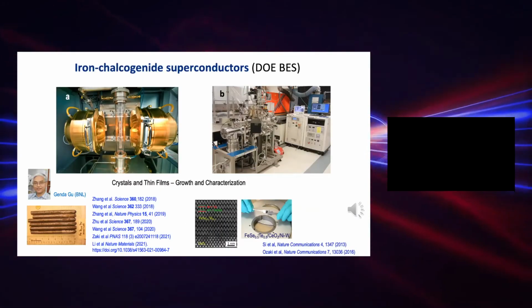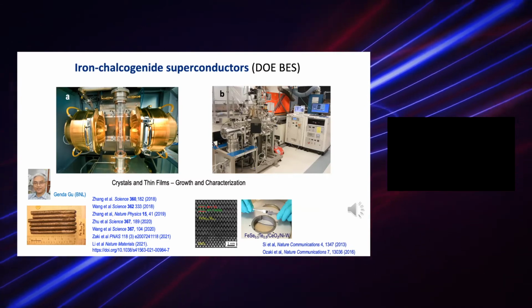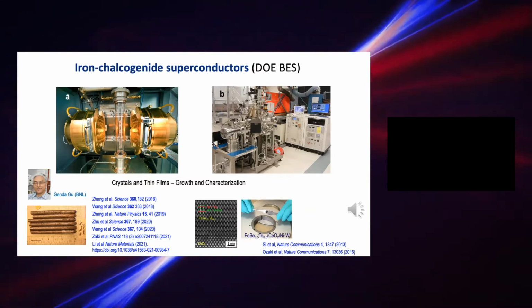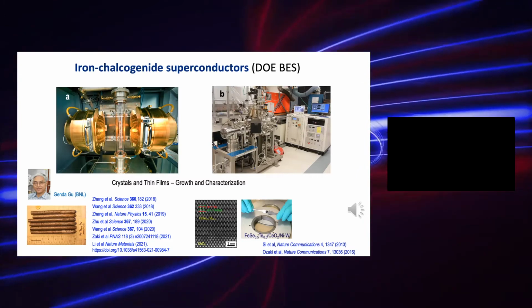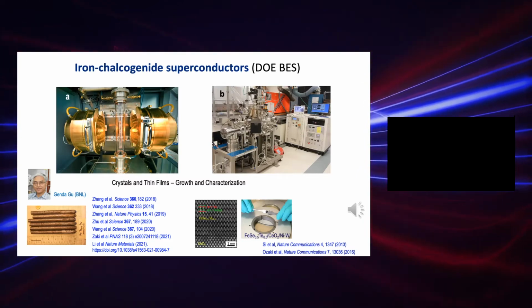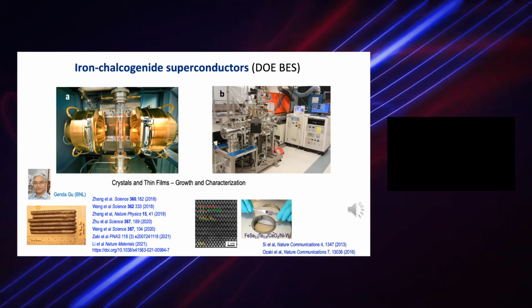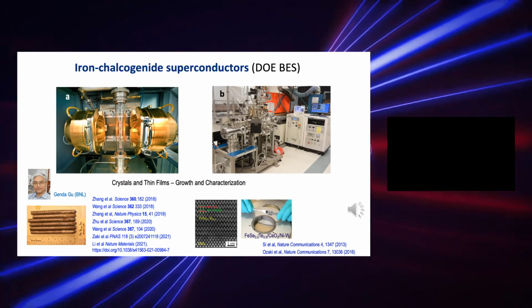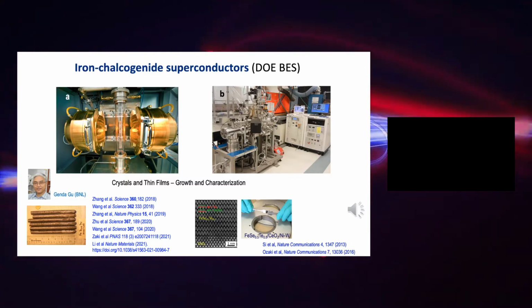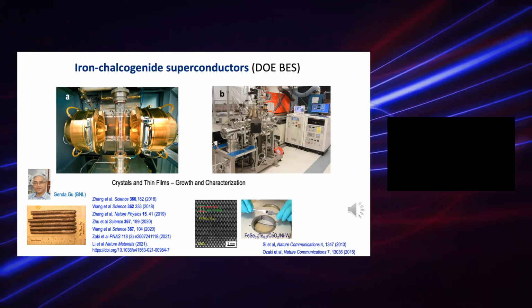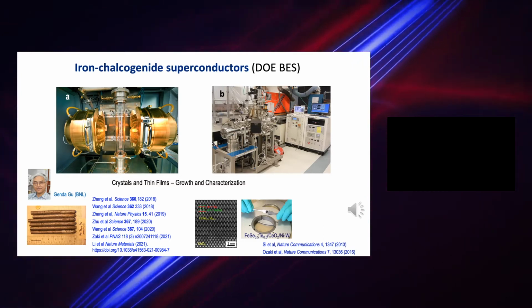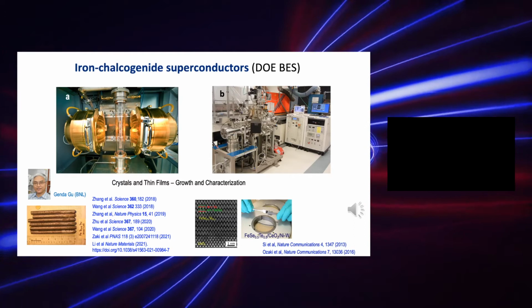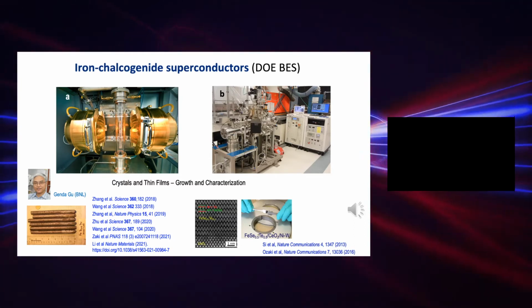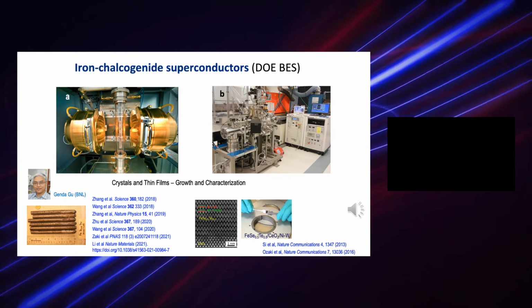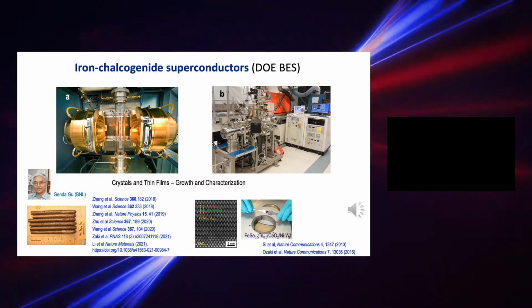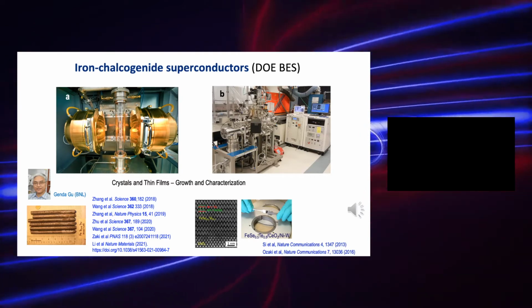Now, our research on iron chalcogenide superconductors is funded by DOE BES. We focus on the growth of single crystals and thin films and characterize their properties. On the single crystal side, we made a large number of iron chalcogenide superconductor single crystals in different compositions, and those are supplied to many groups in the world for fundamental science study. On the thin film side, we're the first group to grow iron chalcogenide superconducting epitaxial films on various substrates with very high crystallinity and superconducting properties. We also made these films on flexible metal substrates.